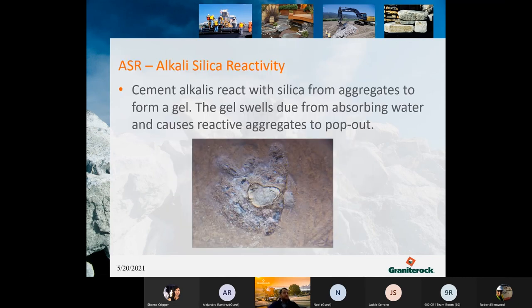To explain alkali silica reactivity a bit more, cement alkalis react with silica from the aggregates to form a gel. And when the gel swells from absorbing water, that causes reactive aggregates to pop out. So really, the aggregate forms a gel and that expands, and that pressure has to go somewhere. So it's actually strong enough to pop out the concrete, which is obviously not good.